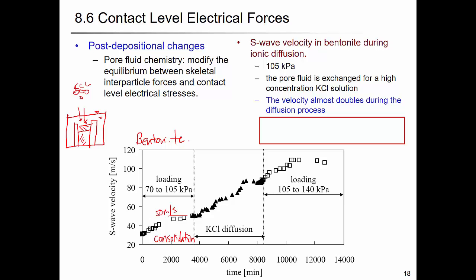So during the KCl, the potassium chloride diffusion, they measure the wave velocity, and you see that it increases to around 100 meter per second, 90 meter per second. And why do you have this increase in shear velocity during this potassium chloride diffusion? So velocity almost doubled during this diffusion process. Then when you have salt dissolved, then it increases the ionic strength of the pore water, right? Then what happens to the double layer of the clay? Clay double layer, does it increase or decrease?